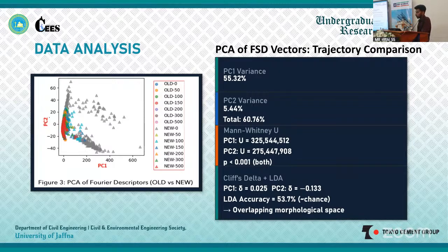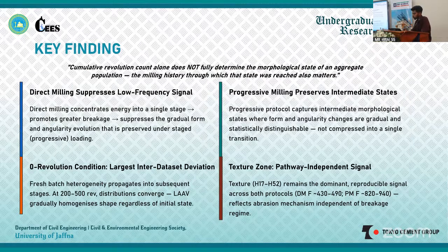These are the key findings. The final particle shape depends not only on the total number of revolutions, but also on how the particle reaches that stage. Progressive milling preserves intermediate shape changes while direct milling compresses these changes into fewer stages. However, the texture zone remains a stable indicator of abrasion in both milling methods.